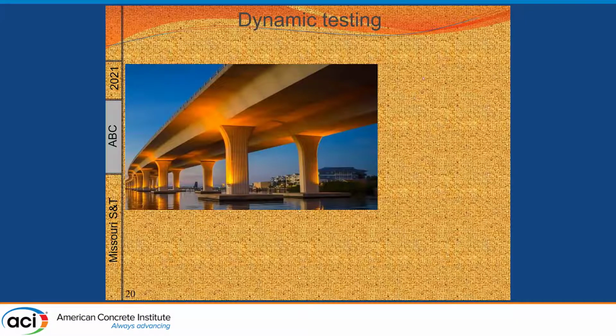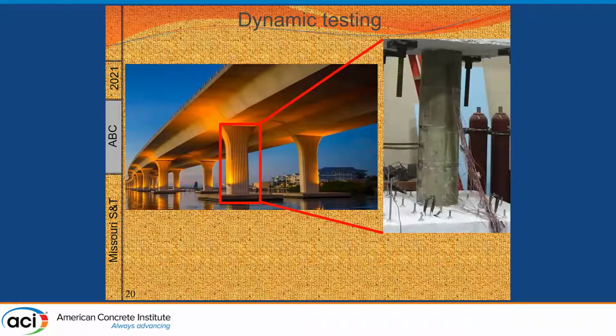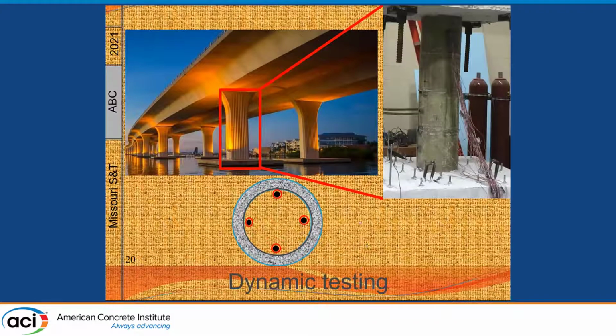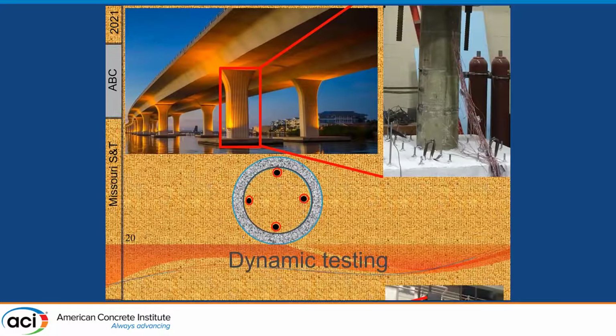So if you think about a bridge column, we take this bridge column on the left there, and we use a 1/5 scale. This column consists of 4 different segments, and each segment consists of the hollow core section. Outside is a glass fiber tube, the shell of concrete, and then the inner steel pipe. And then we also have unbonded post-tension going through the full column.